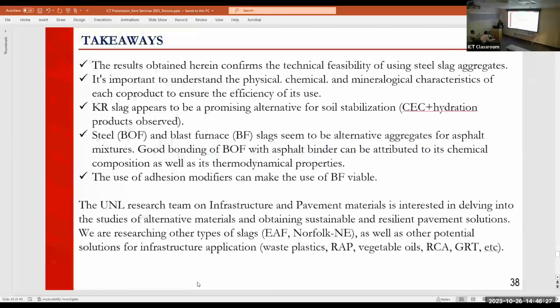And final remarks now. Some results confirm that slag can be an option. It's important to identify which type of slag you are working with to identify the better use. It's important to understand physical, chemical, and mineralogical characteristics of each slag, so you can better define the appropriate use. KR slag was a very nice, promising alternative for soil stabilization due to cation exchange capacity and also some hydration products that were observed. BOF and BF could be alternatives for asphalt.